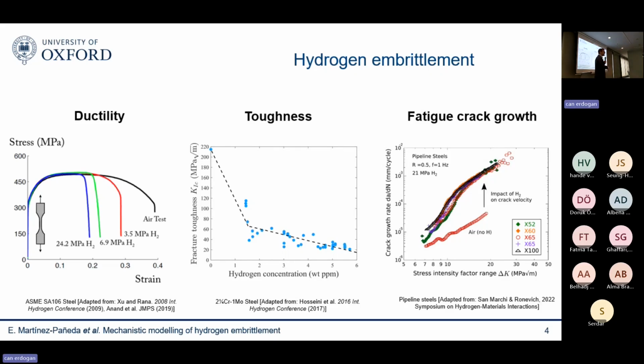And the same goes for fatigue. These are fatigue crack growth rates versus stress intensity factor range. This is in pipeline steels, in air and in the presence of hydrogen gas. You can see, this is a log-log plot, at least 1 order of magnitude increase in fatigue crack growth rates whenever you expose those pipeline steels to hydrogen. So this is, of course, a problem because we need to develop this hydrogen energy infrastructure.